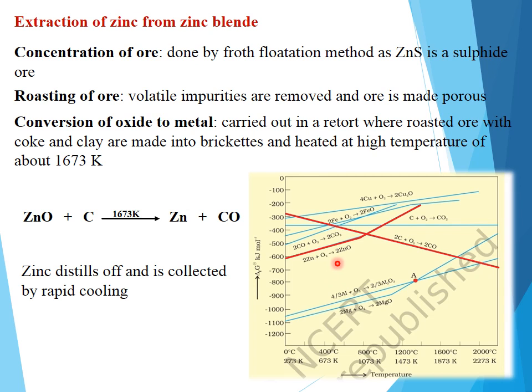So if you go with the carbon and carbon monoxide graphs here, first this graph, carbon dioxide from carbon monoxide, is lying above the zinc graph. It will intersect somewhere here in and around 1600 Kelvin. Till that temperature, you can't use carbon monoxide as a reducing agent. For zinc, carbon monoxide cannot be used as a reducing agent till this temperature.